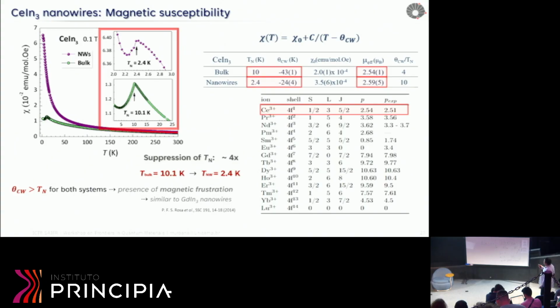And when we analyzed the Curie-Weiss temperature as opposed to this Néel temperature, what we found is always a larger Curie-Weiss temperature compared to T_N for both bulk and nanowires. This indicates the presence of some magnetic frustration there. And if you compare the ratio between Curie-Weiss temperature and T_N, it's more pronounced for the nanowires. It's greater for the nanowires, indicating a more pronounced frustration for the nanowires.